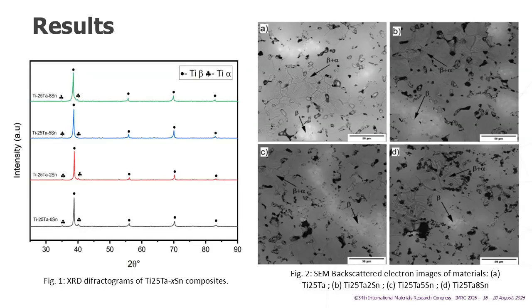As the tin content increases, the areas with beta plus alpha microstructures decrease, likely because these elements form solid solutions with titanium, further stabilizing the beta phase and hindering the nucleation of the alpha phase during slow cooling. The sample with the greatest stabilization of titanium beta phase is the one containing 5% tin, as shown in figure C.